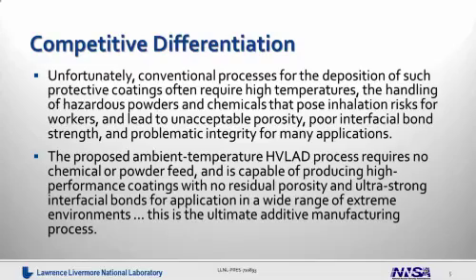How is HVLAD differentiated from other competing technologies? Unfortunately, conventional processes for the deposition of such protective coatings often require high temperatures, the handling of hazardous powders and chemicals that pose inhalation risks for workers, and lead to unacceptable porosity, poor interfacial bond strength, and problematic integrity for many applications. The proposed ambient temperature HVLAD process requires no chemical or powder feed and is capable of producing high-performance coatings with no residual porosity and ultra-strong interfacial bonds for application in a wide range of extreme environments. This is the ultimate additive manufacturing process.